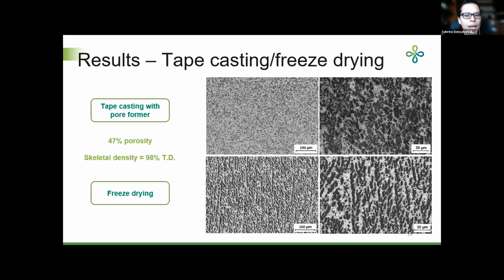So both tape cast and freeze-dried samples had similar values for porosity and skeletal density, but we can see in these images that the pore structure is significantly different. The pore structure of the freeze-dried matrix has more aligned pores in one direction, while the tape cast samples have randomly distributed pores.